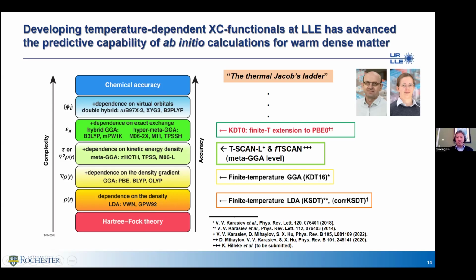But what's the problem if you just directly apply this to warm dense matter? The problem is that all the functionals developed in the 1980s, 90s, or early 2000s are not temperature dependent. You can understand why: condensed matter or quantum chemistry people don't care about 10,000 Kelvin or 5,000 Kelvin. Even at 5,000 Kelvin, most of the material will melt, right? You will get a liquid. That's not interesting to them. So all of these exchange correlation functionals are temperature independent, with no explicit temperature dependency there.